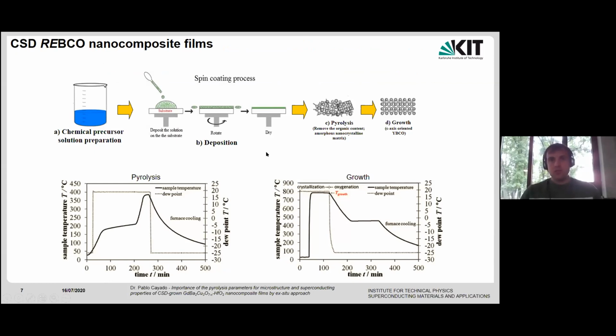So first we deposit the film here by spin coating, or well, by different techniques. We deposit the chemical precursor solution, and then we take this first gel that we have from the spin coating, and we submit it to pyrolysis first to remove the organic content that is inside the initial precursor solution, and then we have to do a second step, which is the growth, which we do in order to get the